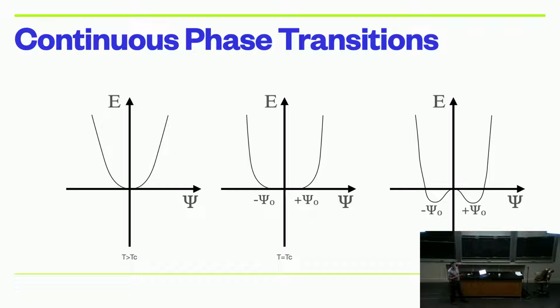And in the case of a ferromagnet, for example, there might be two of those, plus magnetization and minus magnetization, and that kind of leads to different domains in the system, so up spin and down spin along different domains of the ferromagnet. So that's basically how we characterize a continuous phase transition.